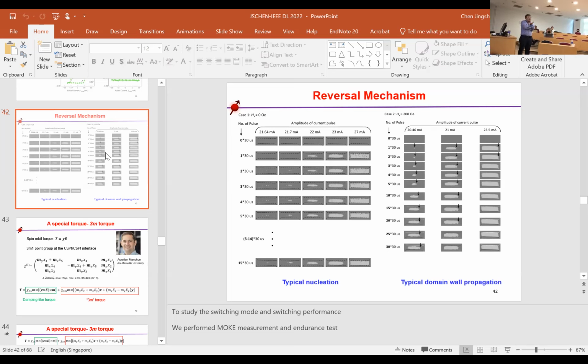But we still find some extra talks, some physics we can find. Not only in the past, for Pt, for tantalum, even amorphous, they can still generate the torque. But here, only the crystal symmetry can generate torque. It all depends on the crystal. That definitely depends on the Bloch wave, electron wave propagation. And this allows me to associate this kind of torque maybe with the orbital Hall effect, because the orbital Hall effect is affected by orbital hybridization, which definitely depends on the crystal symmetry. So the origin is different.